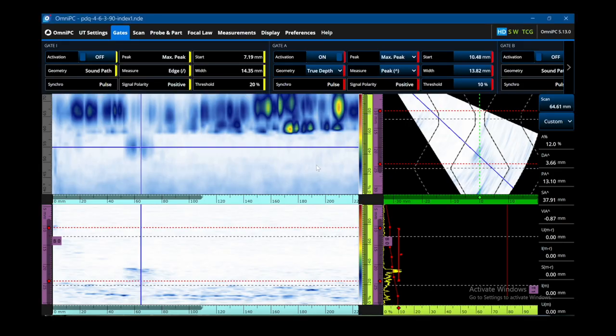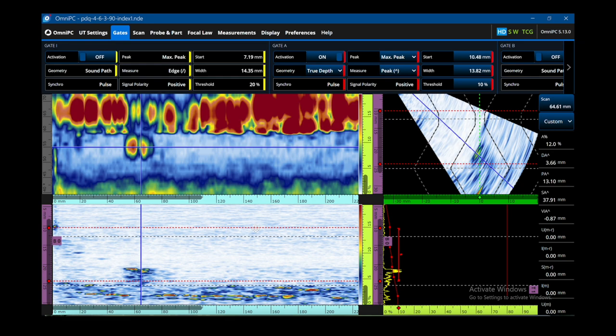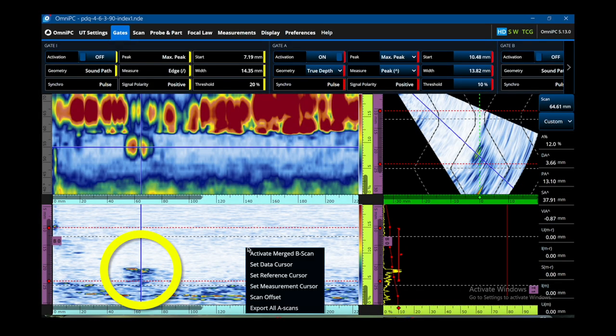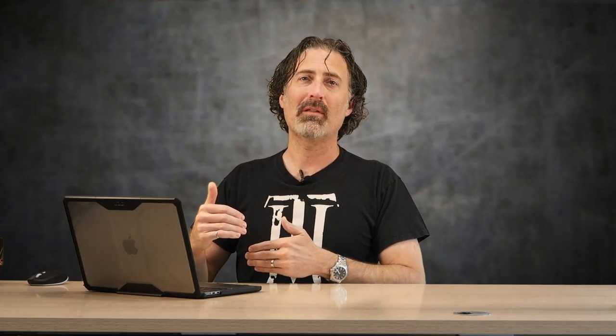Loading up a different file — this is exactly what's happening here with the porosity at around 60 millimeters. Boosting the palette and adding some soft gain, the regular B and C scans look okay as I move the angle cursor around. But when I switch to the merged B-scan, that porosity just vaporizes because there's a competing geometry signal at that particular sound path and the porosity gets lost in there.